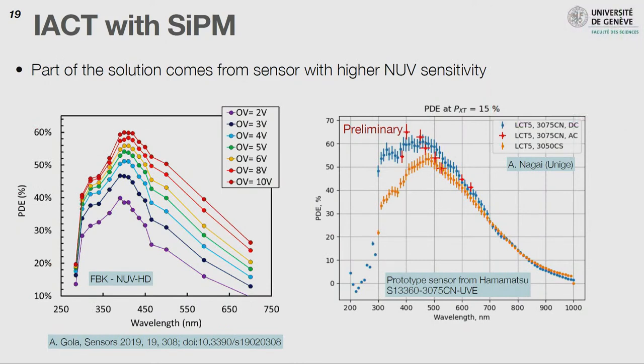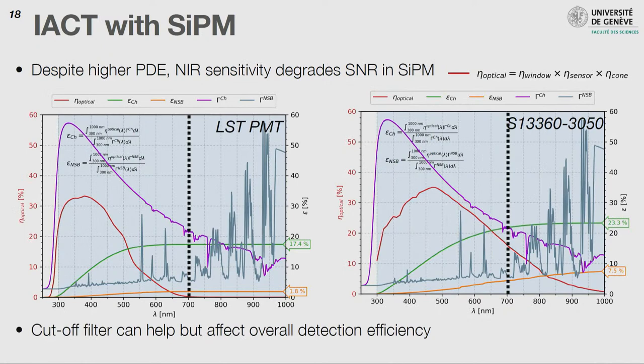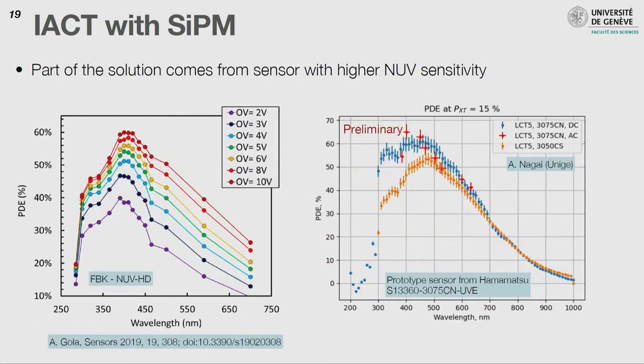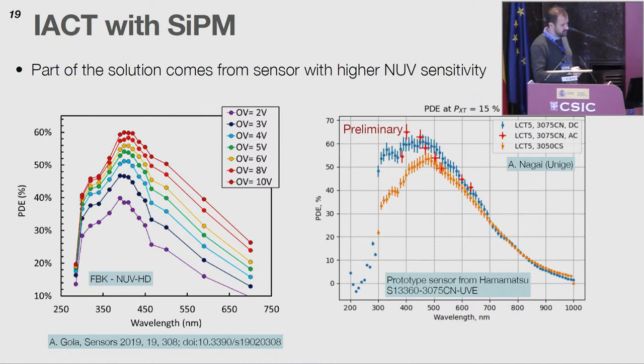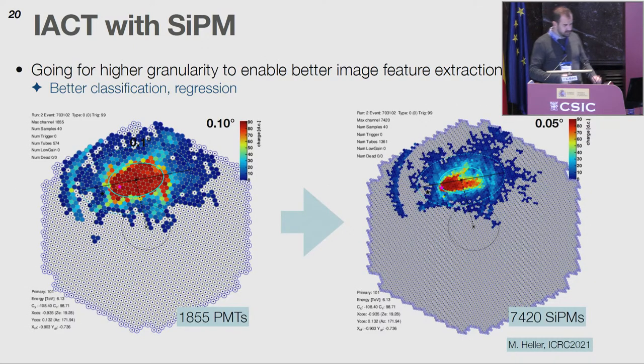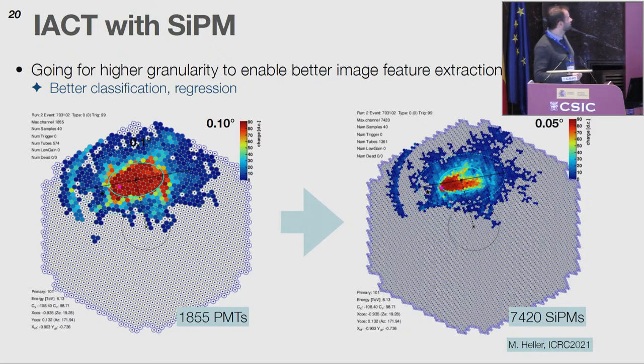One approach is to develop filters, but filters also affect overall efficiency. Pushing photo detection efficiency toward UV is the key challenge here. FBK has done this well for a long time. At the University of Geneva, we pushed Hamamatsu to develop and change their technology for UV enhancement, and in a short time they managed to improve remarkably — by more than a factor — toward 300 nm, while also achieving a very short pulse, which helps fight pileup.